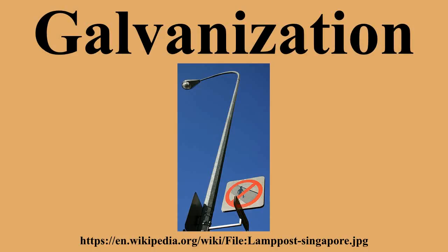Eventual corrosion. Although galvanizing will inhibit attack of the underlying steel, rusting will be inevitable after some decades, especially if exposed to acidic conditions. For example, corrugated iron sheet roofing will start to degrade within a few years despite the protective action of the zinc coating. Marine and salty environments also lower the lifetime of galvanized iron because the high electrical conductivity of seawater increases the rate of corrosion primarily through converting the solid zinc to soluble zinc chloride, which simply washes away. Galvanized car frames exemplify this. They corrode much quicker in cold environments due to road salt, though they will last longer than unprotected steel.